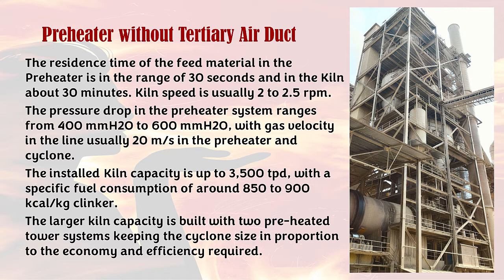The installed kiln capacity is up to 3,500 tons per day, with a specific fuel consumption of around 850 to 900 kilocalories per kilogram clinker. The larger kiln capacity is built with two preheater tower systems, keeping the cyclone size in proportion to the economy and efficiency required.